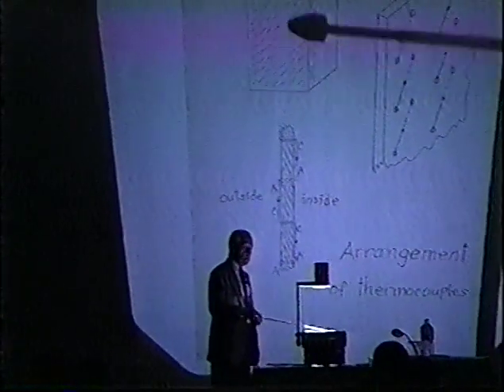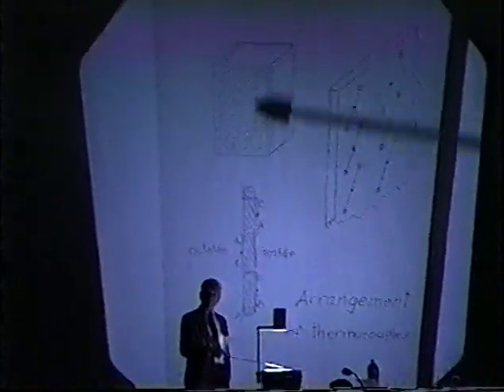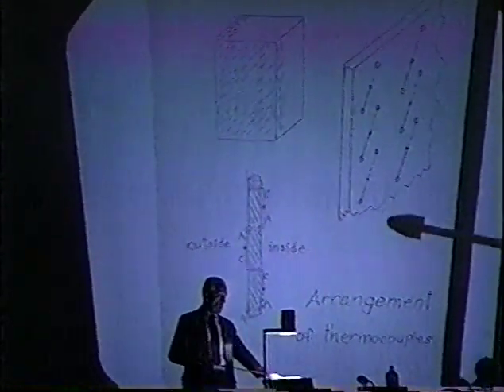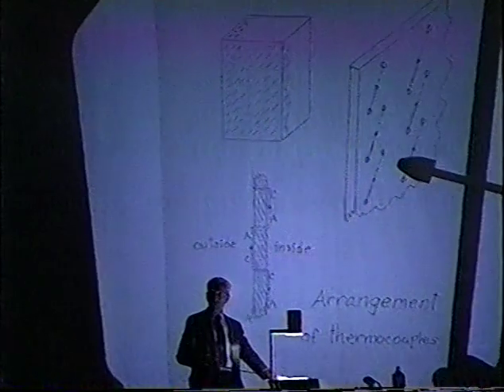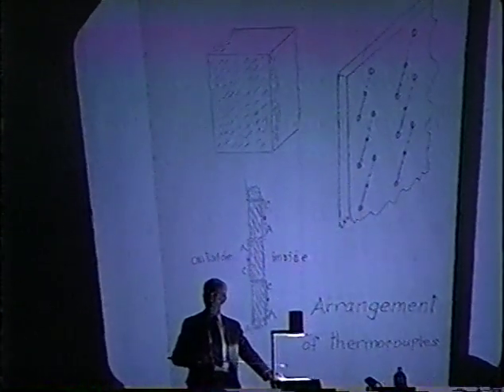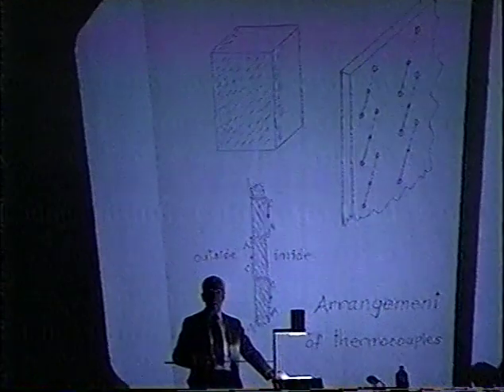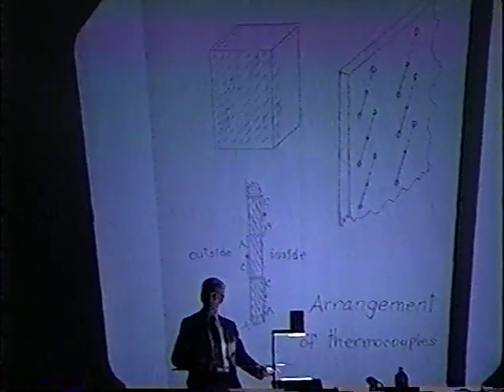Here is a schematic of the box, which is of the order of about that high and about this wide. And each of these spaces is composed of machinable ceramic insulation, electrically insulating material with perforations made by our machine shop, into which is threaded a wire composed of alternate sections of chromel and alumel wire, a very common high-temperature thermocouple material.